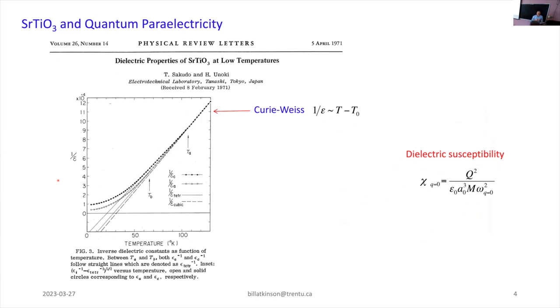And so here, what you're seeing is 1/ε, the dielectric constant. The dielectric constant can be related to the dielectric susceptibility. It's just 1 plus the susceptibility. And the susceptibility can be related to the phonon frequency. The phonon frequency shows up in the denominator; it goes like 1/ω² at the zone center. So you can think of the plot of 1/ε as just a plot of the phonon frequency squared at the zone center. Okay, to a good approximation, that's what you're seeing.